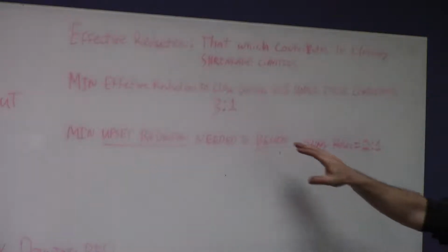Under ideal conditions, which you certainly can have, this is one of those times where you can get ideal conditions in the forging world, would be 3 to 1. That's the absolute minimum that you're going to need. And I showed earlier how we arrive at that number, and you'll see it on the cheat sheet that Dr. Metzloff put together, how the center line is worked 1/3 the length of whatever the die bite is that you're taking. So that, of course, means that you have to make 3 consecutive passes to get the entire length of the object worked at the center line, so that's where the 3 to 1 comes from.